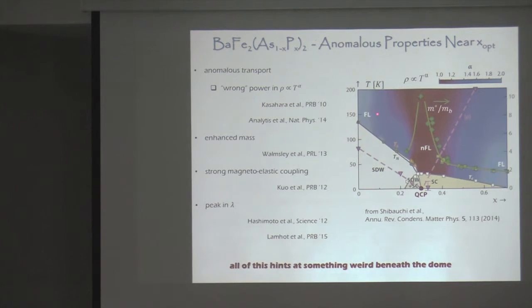For example, if you look at transport, it has the wrong power in temperature above optimal doping in the normal phase. If you try to measure the mass by a variety of means, and that's not a trivial thing, then you see that the mass increases, I don't want to say diverge, but it increases where the maximum seems to be near optimal doping. There are other effects that you can see, like there's strong magnetoelastic coupling, which is also weird in this material. And then there's this peak in lambda, which is interesting because it happens below Tc. So all of this points to something weird happening around this point.